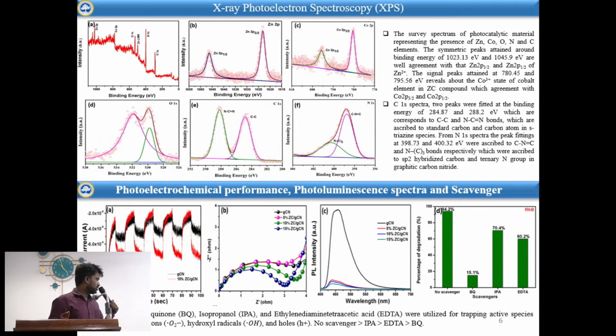So we have compared with pure g-C3N4 as well as the 15% graphitic carbon nitride composite sample. Here we can see a higher photocurrent, which implies the charge transferring property from the valence band to the conduction band of the material. And figure B shows the impedance spectra, where the resistance of the material after doping has been reduced compared to the pure one. So through this we can confirm that the charge transfer property is enhanced with respect to the composite sample.